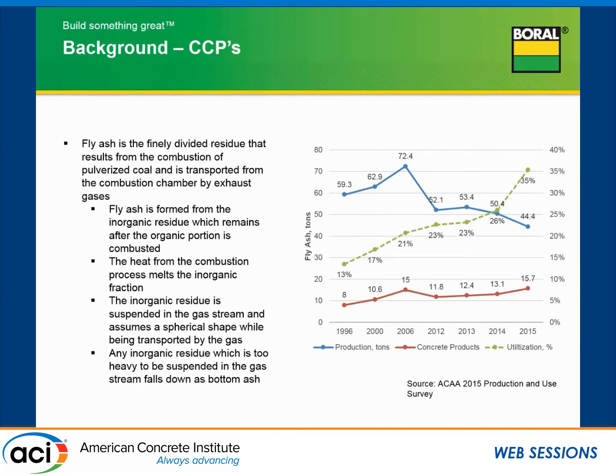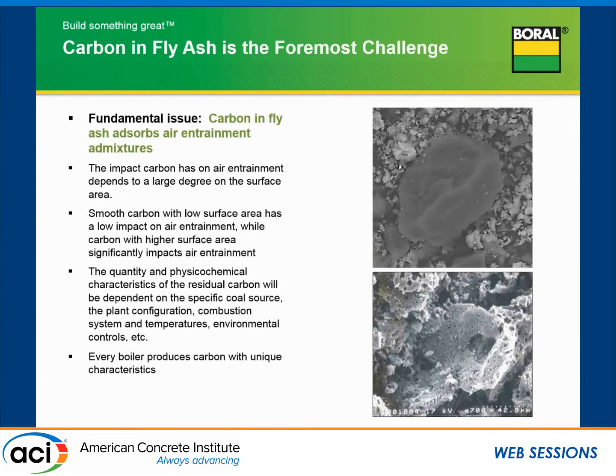What that means is we're using fly ash that probably hasn't been used before, and that fly ash must be beneficiated to be used in concrete. Carbon is our main bugaboo in the industry. It comes across as residual carbon in a typical coal-fired plant. Carbon causes problems in concrete because it absorbs the air-entraining admixtures put into the ready-mix concrete. It has an affinity for those types of admixtures, so in a simple way — it absorbs those admixtures where they're not available to generate air in the concrete.